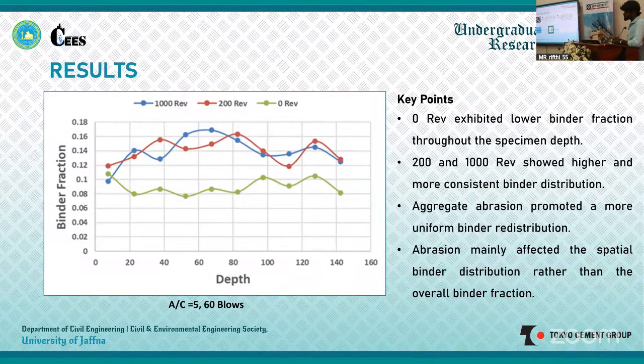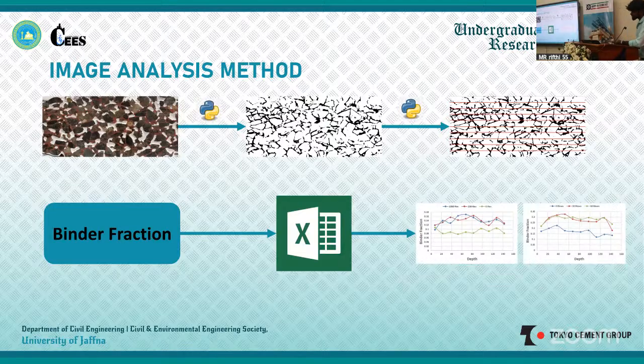The panoramic images were processed using a Python-based image analysis program. First, each panoramic image was converted into a binary image, where the black region represents the binder and white represents the aggregate and pores. Next, the binary image was divided into 10 equal horizontal layers from the top layer to the bottom layer. Then the binder fraction was calculated separately for each layer. The Python program automatically generated an Excel file containing the binder fraction values for all 10 layers of the specimen. Finally, these data were used to evaluate how aggregate abrasion and compaction influence the depth-wise binder distribution in pervious concrete.